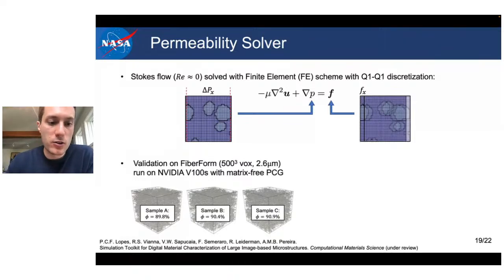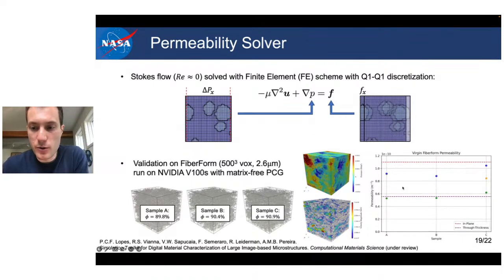This was actually implemented through an NVIDIA kernel. Pedro knows all about this, and the validation campaign that we ran on Fiberform is shown here for 3 different samples. We also had experimental values for a similar type of microstructure. So these are some of the results that we obtained, where, starting from the middle, this is what the PuMA function, or this GPU implementation, gives you back, which is a pressure field and a velocity field. And then from these, you can backtrack the effective permeability.